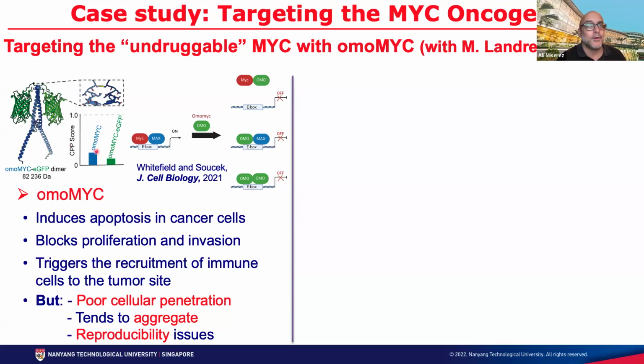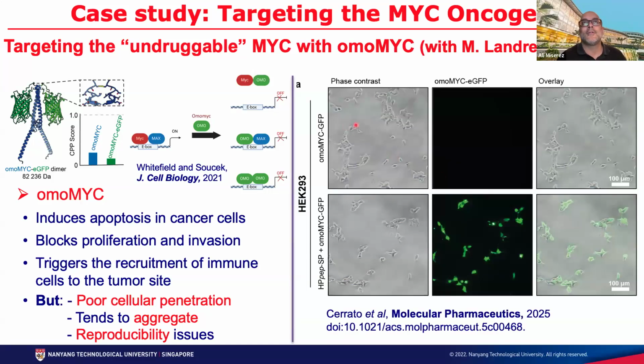But a few years ago, some group in Spain came up with this peptide called omoMYC, which can in principle target this oncogene and prevent this dysregulation. But the problem is that this peptide has very poor cellular penetration. It tends to aggregate, and there's also some irreproducibility in the literature. So the idea was, can we actually deliver this very promising peptide with our system? And so the answer is yes.